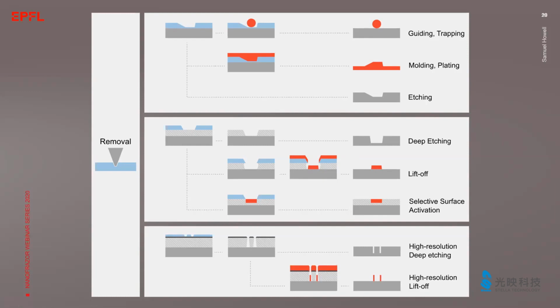And another application of the 2 layers is that one can selectively activate a functional material under the thermosensitive resist. So for example, in this case, a material is protected under the PPA, and the PPA is opened, and then, for example, with an oxygen plasma treatment, the material can be activated and the PPA can be removed afterwards. And like this, selective nanostructures on the surface can be created. To achieve the highest resolution possible, it is often required to have 3 layers, and there it's necessary to have an approximately 2 to 3 nanometer thick hard mask between the PPA and the organic transfer layer. But also here, deep etching and high resolution lift-off are possible.